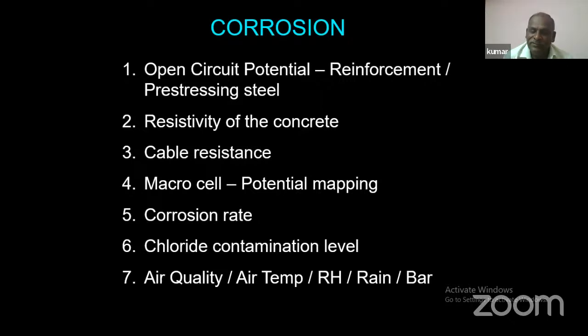Then you know very well air quality, air temperature, relative humidity, rainfall level, barometric pressure and so on. All these things contribute to the deterioration of your structure. So you have to have these kinds of parameters. Then you can add other parameters for measurement, which are ultrasonic pulse velocity. You can use the rebound hammer to identify how much deterioration has happened, and use the phenolphthalein indicator to identify whether your concrete is carbonated or not. Like that, many other new equipments have also come that we can use for condition assessment of your concrete structure.